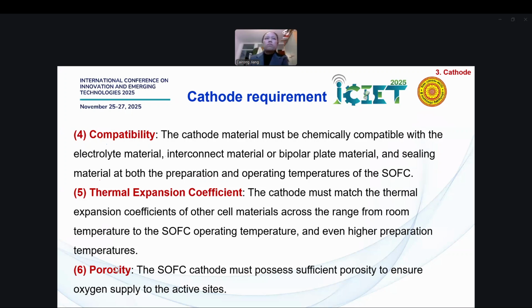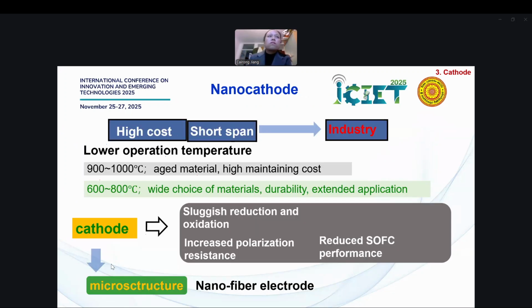And according to these requirements, we need to think about how this whole cell works. First is the temperature. It seems there's a trend now to reduce the working temperature from 900 to 1,000 degrees down to 600 or even 800 degrees, what we call medium temperature. By reducing the temperature, we have a wider choice of materials. We can have better durability and extended application. But when you reduce the temperature, the cathode could have problems like sluggish reduction and oxidation, and the polarization resistance will of course increase, because all these materials work well at high temperature. If you reduce the temperature, the activity will be reduced too, and of course you cannot get a good cell performance.